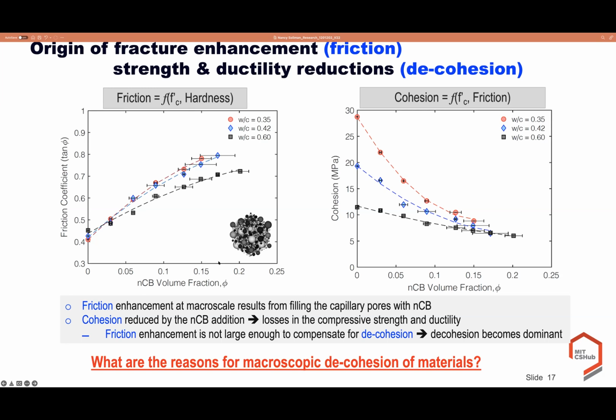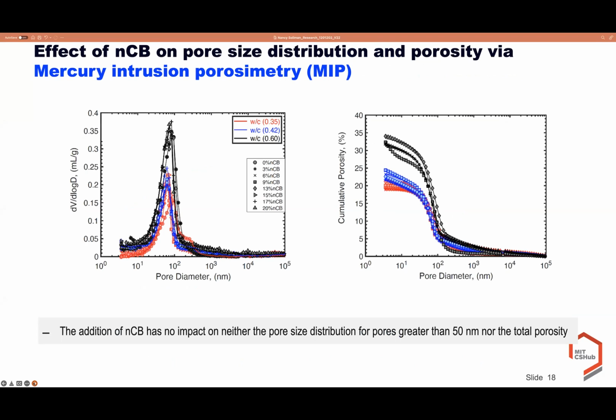So this leads us to ask this question: what are the reasons for the de-cohesion of the material? To answer this question, we study the effect of nanocarbon black on the pore size distribution and the porosity of the material. And what we observed here is that the addition of nanocarbon black doesn't have any impact on the pore volume distribution or on the cumulative porosity for pores greater than 50 nanometers, which is the limitation of mercury intrusion porosimetry.